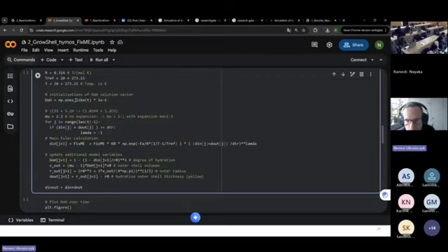And then from the stoichiometry, we calculate the mu expansion, so 2.3. If you want to simulate the C3S reaction, that is it. You can simulate any other reaction, then you should change the mu factor, which you should model based on the stoichiometry, which I showed you yesterday how to do.